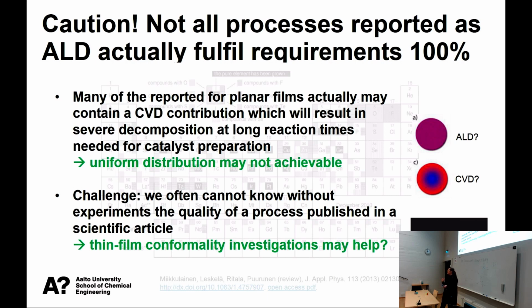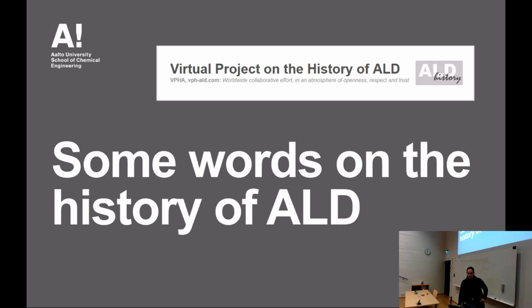portion, let's say, of decomposition in this reaction, so that the reactant would not react fully in a saturating way, but there would be a continuous component, you might not see it on these samples, but you would see it in our porous materials. So it's very good that there are so many processes where we can start from, but I wouldn't make any promises that they work before I have tested it myself.